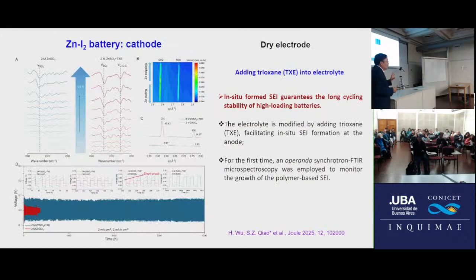Okay. So now, in this battery, if we don't add anything in the solvent electrolyte, you can see the short circuit is very fast, right? We must consider making the battery last longer, so run a long time. For this reason, in this system we add this molecule. After we add this molecule, you can see we can run 5,000 hours, 4,000 hours. So what is the reason? After we add this TXE, we can measure the SEI film produced on the anode.